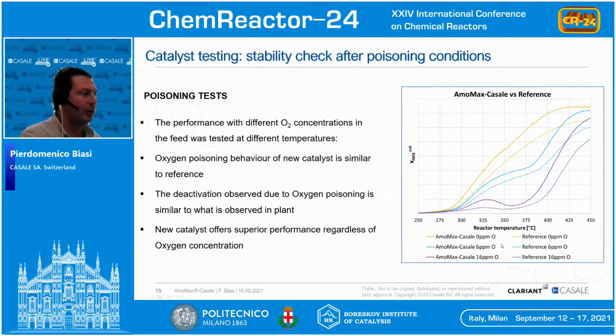As you can see, these are reports of some tests, but we also did between 0 and 6 ppm and between 6 and 16 ppm. There are three main steps: 0, 6, and 16 ppm. 6 ppm of oxygen is the limit that the catalyst producer usually gives to plant managers as the maximum amount of oxygen to operate the plant with. So we tested the catalyst with this amount of oxygen in a broad range of temperature to see the effect, where it was limiting, where the problems were.